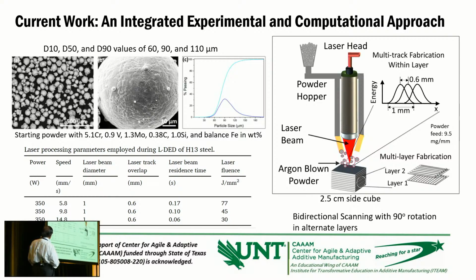If you don't want elongated grain, then we scan the beam in one direction in one layer, rotate it through 90 degrees, and scan in another direction in the second layer, and then keep repeating that alternation of the scanning direction from layer to layer. That way you create a disruption of the epitaxial grain growth through the layers, and you get a little bit better distribution.